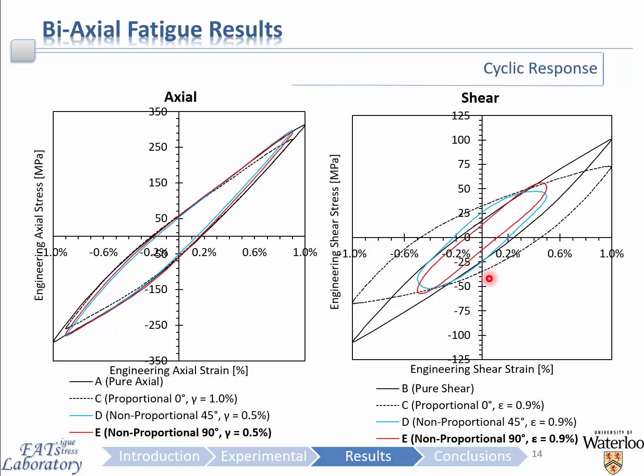Finally, when we increase this non-proportionality to be out of phase by 90 degrees, we can observe that once again, the axial response remains virtually identical to all of the previous cases, whereas the shear response once again has been affected by the increase in this non-proportionality. Important to note is that the plastic strain energy density for the shear response, which is signified by the area enveloped in these hysteresis loops, has decreased with increasing phase angle, and this is an important observation which I will discuss later.